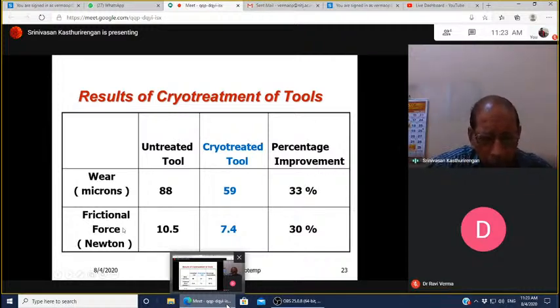The frictional force in newtons, again, untreated tool has got 10.5, whereas the cryotreated tool has got 7.4, and the percentage improvement is about 30%. Okay, so cryogenic treatment not only improves the microstructure, for example, dimensional stability is also introduced by the process in this material. ISRO has been one of the important customers for this type of cryogenic treatment. There are some pressure transducers, the diaphragms, which are cryogenically treated and then used in their systems.